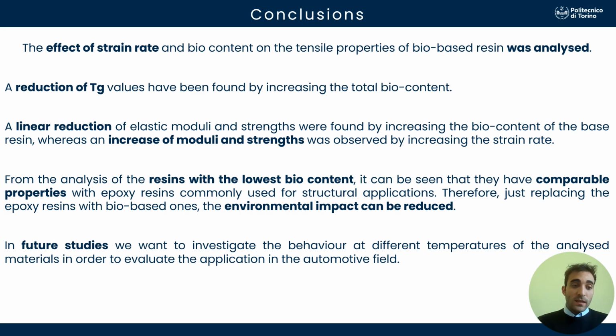Most importantly, from the analysis of the resins with the lowest bio content, it can be seen that they have comparable properties with epoxy resins commonly used for structural applications. Therefore, just by replacing the epoxy resins with bio-based ones, the environmental impact can be reduced. In future studies, we want to investigate the behavior at different temperatures of the analyzed materials in order to evaluate the application in the automotive field.